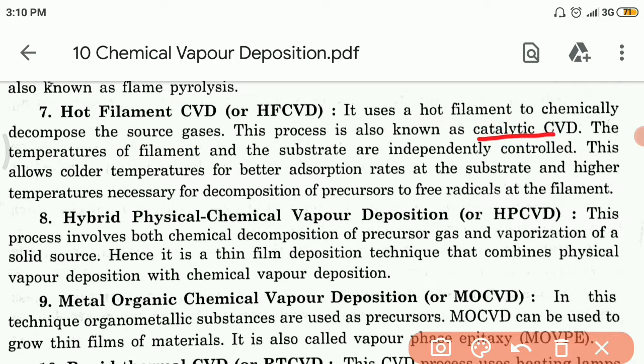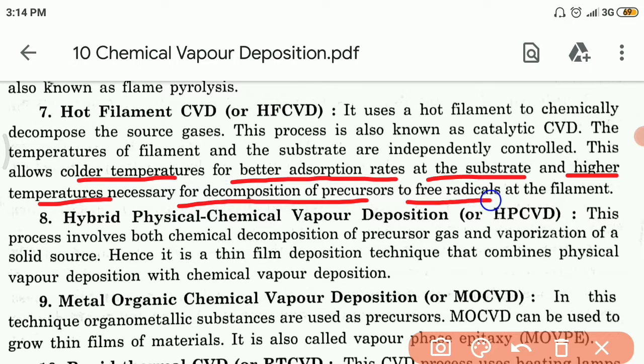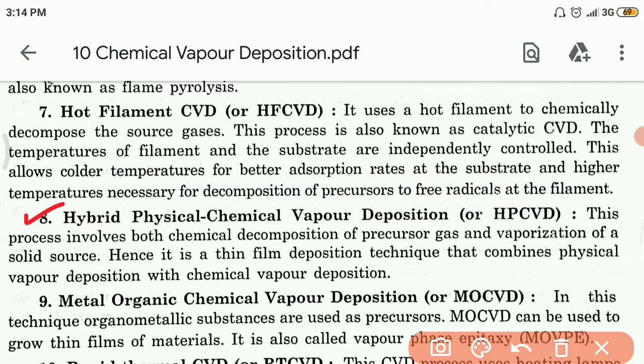Here the temperatures of the filament and the substrate are independently controlled, and this allows colder temperatures for better adsorption rates at the substrate and higher temperatures which are required for decomposition of precursors to free radicals at the filament. Now the next one is the hybrid physical chemical vapor deposition, that is HPCVD, and this process involves both chemical decomposition of precursor gas and vaporization of a solid source. Hence it is a thin film deposition technique which combines the physical vapor deposition along with the chemical vapor deposition. So it is a combination of both physical and chemical vapor deposition processes.